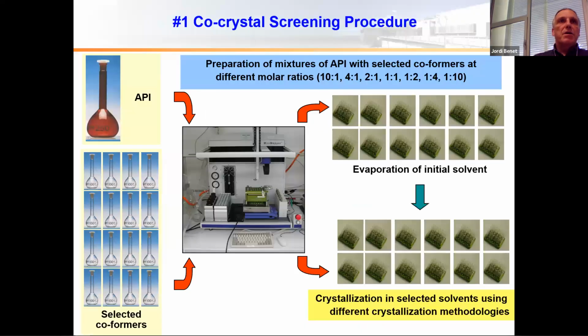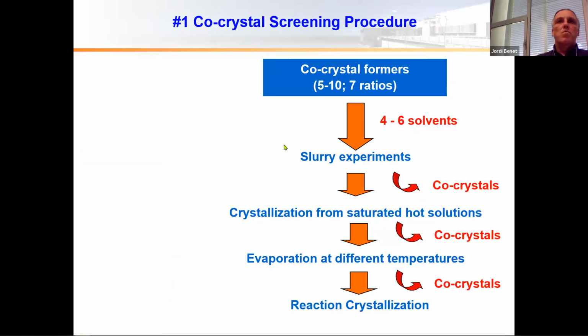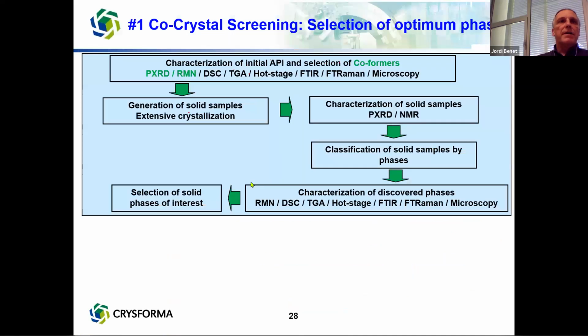In a co-crystal screening, we prepare our active pharmaceutical ingredient and mix it with different coformers, which are possible molecules that could form a co-crystal. We prepare different solutions, make different crystallizations, and finally try to characterize the obtained compounds. We do different experiments like slurry experiments, crystallizations from different conditions, melting experiments, and grinding experiments. Initially, we characterize the starting product and the coformers with the available analytical methods, especially powder diffraction and Raman spectroscopy, and then we start with a massive generation of solids.